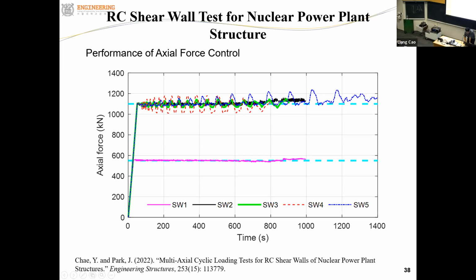Okay? And this one shows the result from the unidirectional as well as the bidirectional loading test with a different loading pattern. The black line shows the unidirectional case with 1,100 kilonewton axial force, almost constant, which is good. The remaining part shows the axial force controlled during the bidirectional test with a different loading pattern. We have this kind of fluctuation of the force because we didn't consider the velocity feedback for this test for the axial force control. If we consider the velocity feedback, then definitely we would be able to get better axial force control. But overall, we were able to achieve successful, satisfactory control of the axial force.